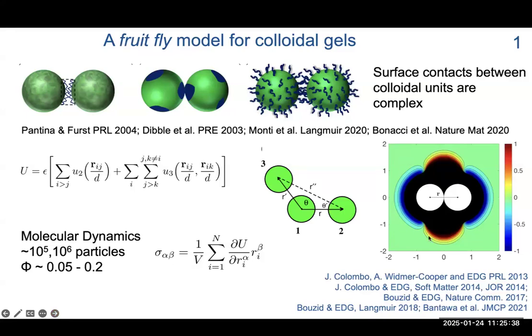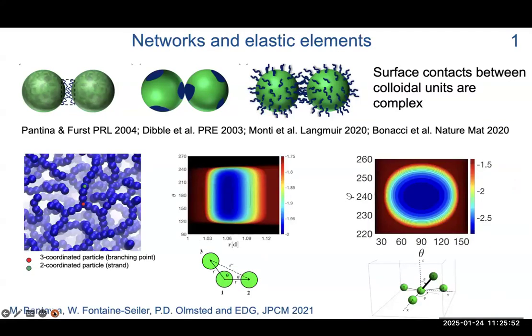Imagine if it's everything blue, so the particles can stick everywhere and there is not this type of stiffness associated to the bond, then I will favor the formation of compact aggregates. But if I vary that angle, the energy cost, I can change the structure a lot. So this is one specific choice of these parameters that we have studied a lot, and that forms this type of network that you can see here.